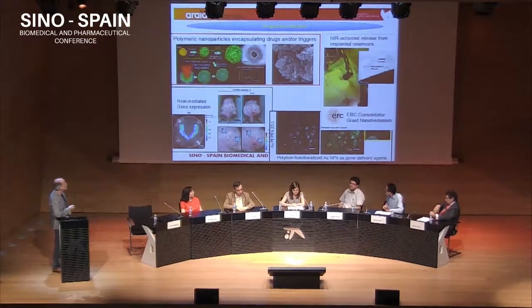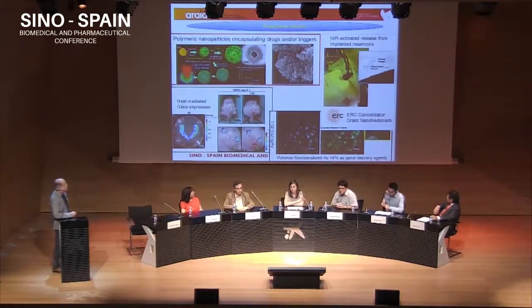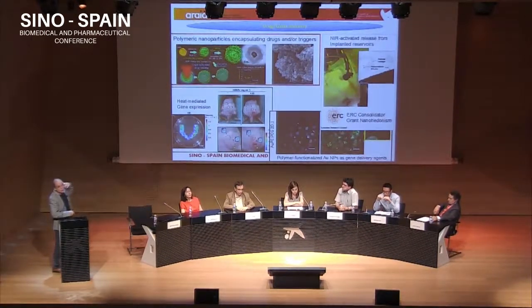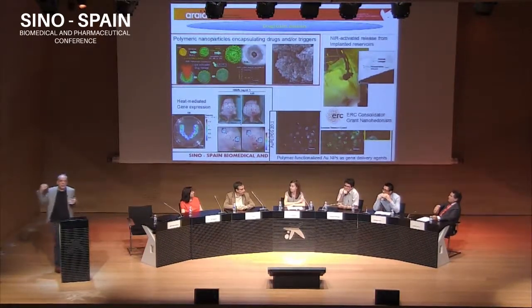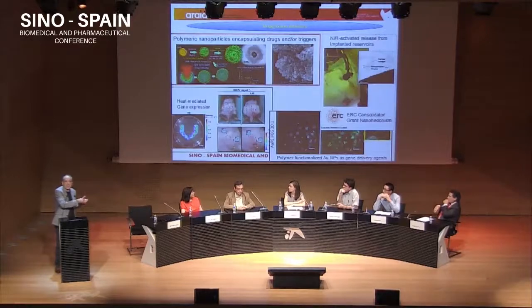And finally, we also have near-infrared activated release from implanted reservoirs. This is a collaboration with MIT, with the group of Bob Langer. And here, this is a rat that has an insulin reservoir that we can activate from the outside using a laser, thanks to a membrane that is a temperature-sensitive polymer membrane that also contains gold nanoparticles as triggers. So remotely, from outside the body, we are able to use an infrared laser to heat the nanoparticles, heat the polymer, it opens up and releases the insulin. We were able to control the glucose level in a diabetic rat during 14 days.